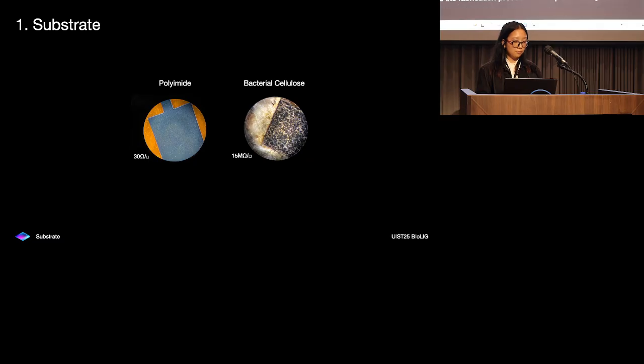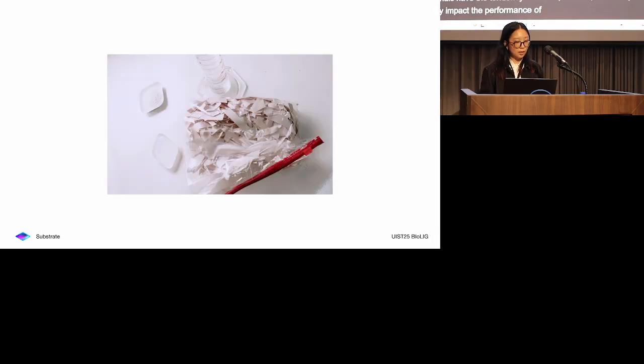Traditionally, laser-induced graphene is on a synthetic material called polyimide, yet the inherent high carbon content of biomaterials make them especially suitable for this fabrication technique. However, natural materials have the tendency to shrink, deform, and warp, which can all negatively impact the performance of LIG. One core contribution of this paper is to innovate on bio-based material that prioritizes consistency. Our substrate consists of 4 components.